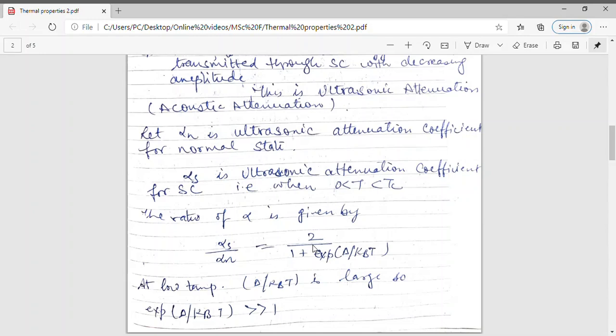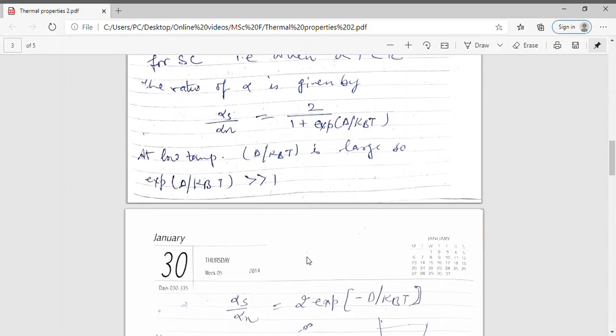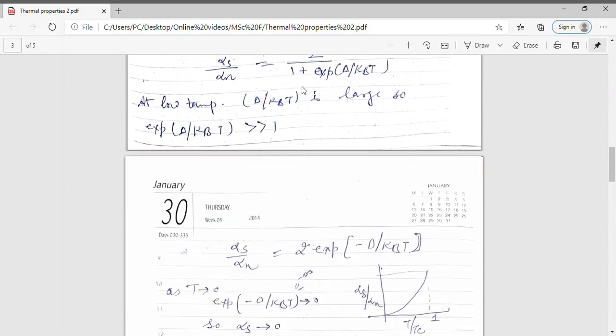Now I am considering a temperature range which is very low. As temperature is low, the factor delta upon kBT will be large. Hence, the exponential value which is in the denominator will be very much greater than 1, so that we can neglect 1 as compared to this exponential term. So our expression will become alpha s to alpha n is equal to 2 exponential minus delta upon kBT.